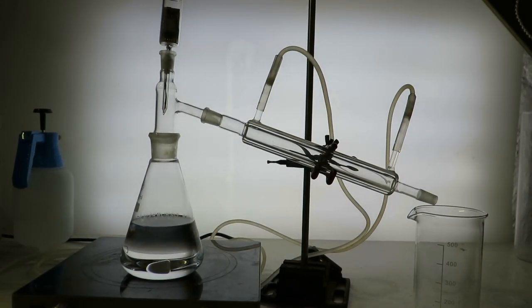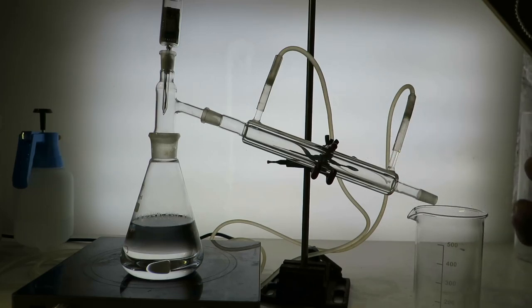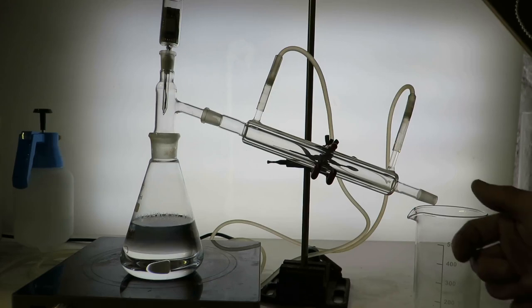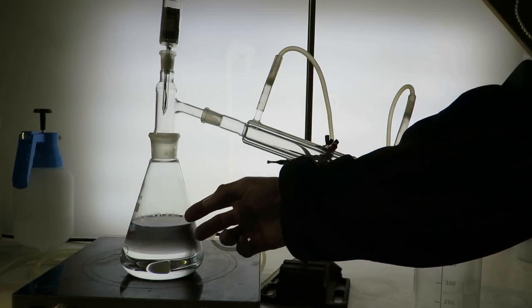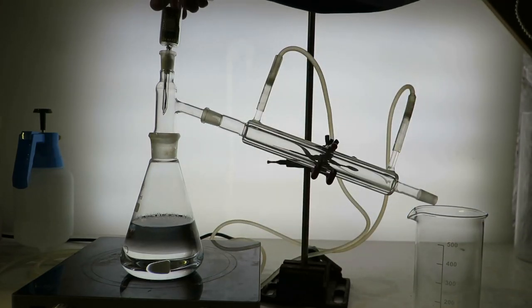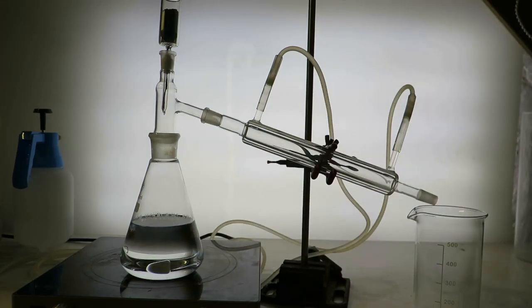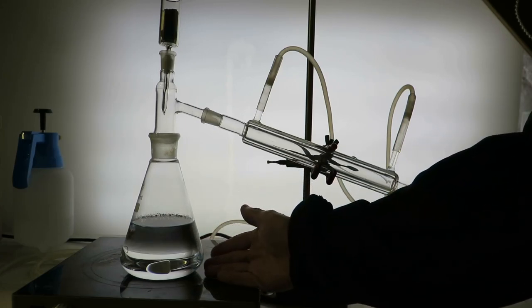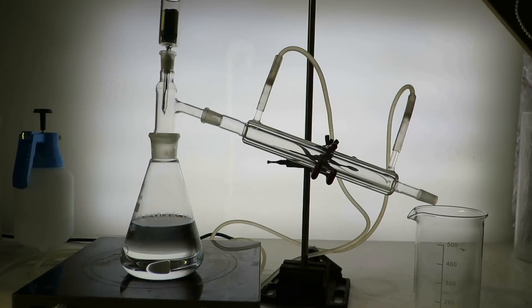I think I have extracted everything that I could from the gel. It was a very painful process, took me maybe even five hours so I did not record it. I extracted it first with water and then with DCM which is here. Then I washed the DCM with sodium hydroxide to get rid of any unreacted methacrylic acid. I dried it, so now I will distill it to quite a low amount then evaporate the rest.